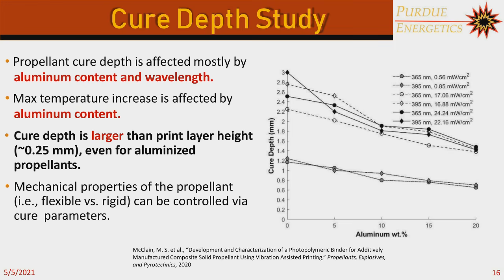For us, knowing that this will cure much deeper depending on the parameters we use, especially with highly aluminized propellant formulations, means that we don't really have to worry about regions of uncured propellant. This also means that maybe we can 3D print several layers before curing, which might reduce our print time. We also know that with this photopolymer mixture, we could potentially swap out some of those components to tailor other properties more, whether cure properties or mechanical properties.